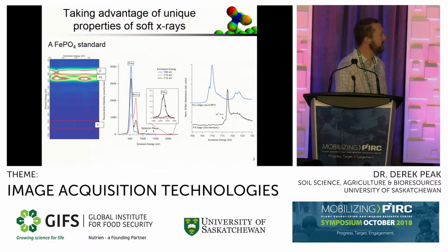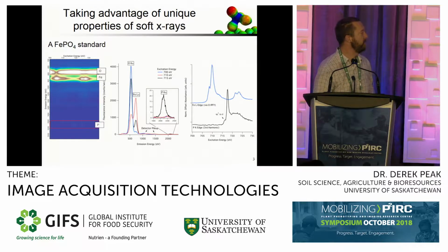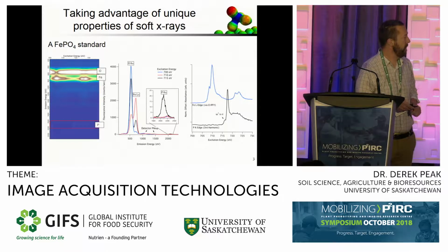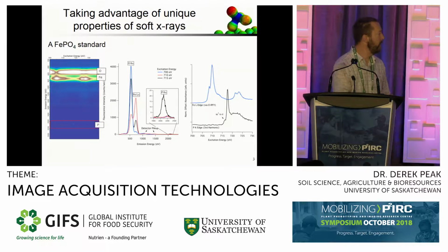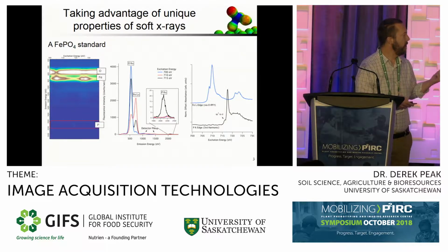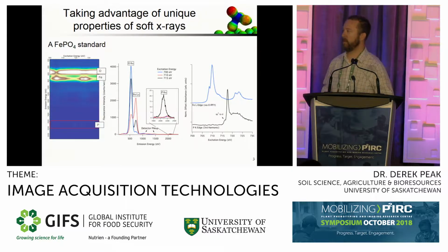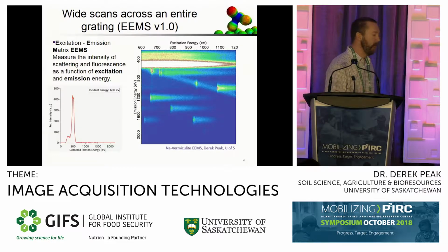And so you can do a soft X-ray experiment where you think you're looking at iron. Anyway, if you look at that horizontal slice of iron, that's the measurement we were trying to make, but in fact there's some phosphorus fluorescence that's really well resolved on the emission line, and you can pull out a phosphorus K-edge spectrum that's actually 2100 to 2200 eV. And so in some ways, you're getting an extremely rich set of data by the fact that your fluorescence lines overlap.